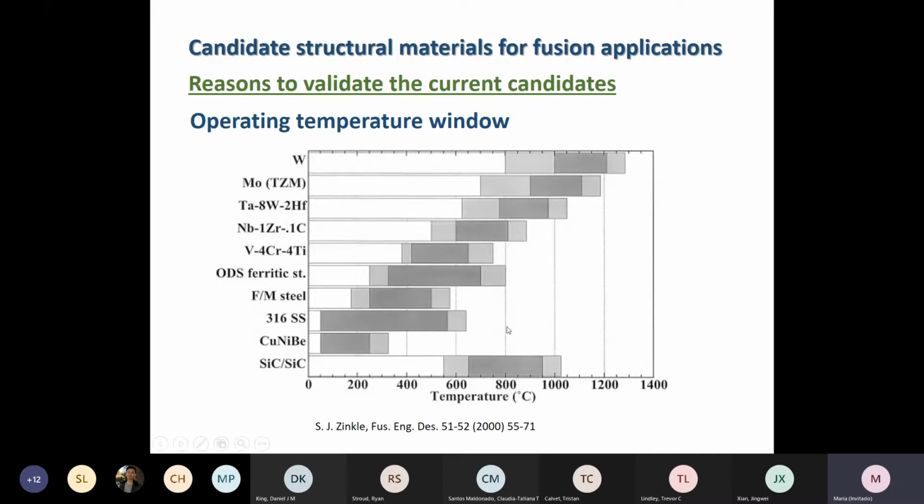And it means that it's one step forward from where we mainly were. And here you can see the silicon-based materials are around here, in a very interesting temperature range. And on top of that are the tungsten and tungsten alloys. They can work at the highest temperature, and that's why they are used as directly plasma-facing materials inside the reactor. But there are many parts in the reactor where specific materials need to be located.